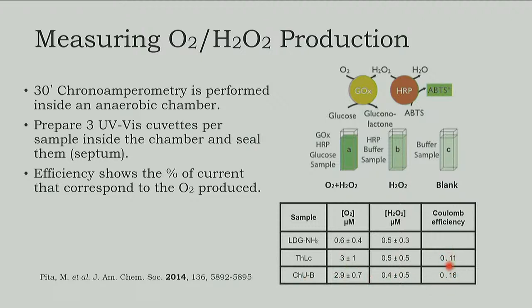But the Coulombic efficiency for the mutant one was a little bit higher. Anyway, 10% of Coulombic efficiency is not a very optimistic value, but it's good enough to prove that the system can be done. And of course, there is a lot of things to research here for different kinds of enzymes containing copper that can make this reaction.